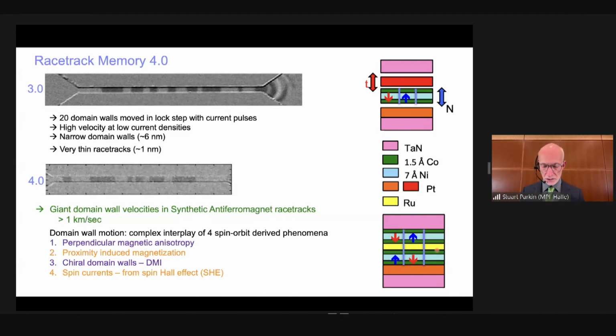And in the early days of spin valve, when I was working on spin valves, I discovered a long-range oscillatory coupling through all the transition metals and noble metals in the periodic table. And by choosing the proper thickness of ruthenium, this leads to an extremely strong anti-ferromagnetic coupling, so that the magnetization in the lower racetrack, for example, this blue region, will be exactly mirror imaged by the same moment in the opposite direction in the upper racetrack, meaning in aggregate there's no net magnetization. Therefore, we've eliminated all the dipole fields.